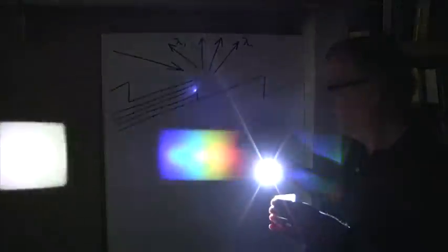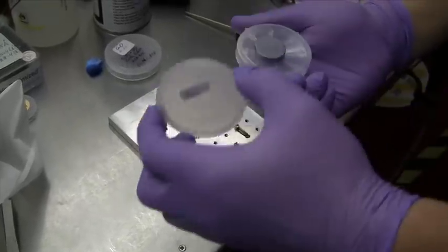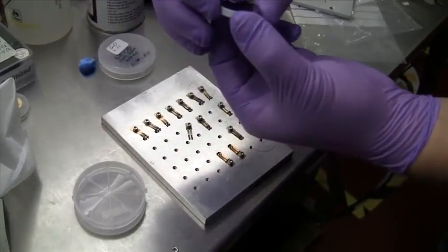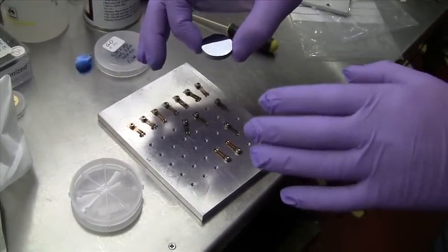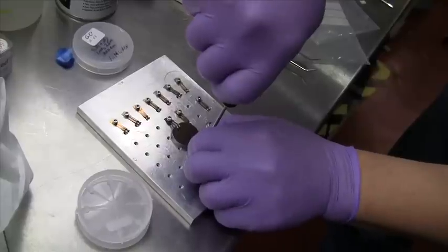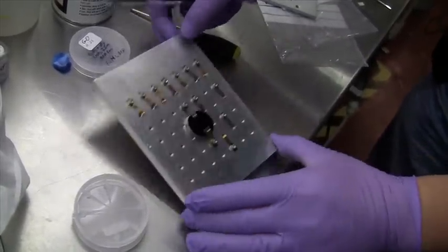Scientists have used diffraction gratings to disperse light for more than 200 years. They are actually two-dimensional surface structures, because they are fabricated by making parallel lines on the surface. What we are trying to do is develop a new kind of X-ray grating, which are three-dimensional structures, and we fabricate them by depositing a multi-layer coating on a sawtooth substrate. Such three-dimensional structures can have much higher groove density and can operate in high diffraction order.